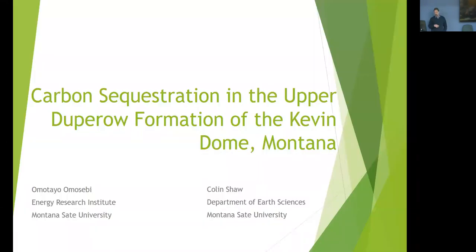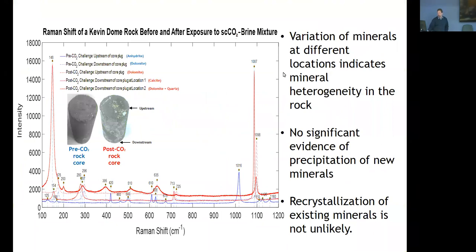Tayo, who is also working with Colin and the Energy Research Institute, they have looked at changes in mineralogy in samples from Kevin Dome, which is a dome that naturally contains CO2 up in north central Montana as part of the Big Sky Carbon Sequestration Partnership. And they have also used Raman spectroscopy, among other techniques, to look at rocks before and after exposure to supercritical CO2 brine mixtures. And what they basically saw, and these conclusions are, as far as I know, not based solely on Raman, is that there were no new minerals that developed during the supercritical CO2 exposure, but that there appears to be a recrystallization of certain minerals after or during CO2 exposure through dissolution and reprecipitation.